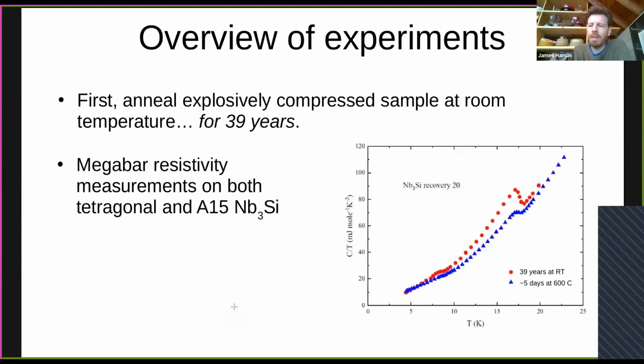So let me describe the experiment we did. We took the explosively compressed sample, and the first thing we did was anneal it at room temperature for 39 years. So this sample was made some time ago. We then remeasured the sample some 39 years later, and it still showed a perfect bulk superconducting transition. So this is really stable, even though it's not the stable phase, it persists over a very long period of decades.